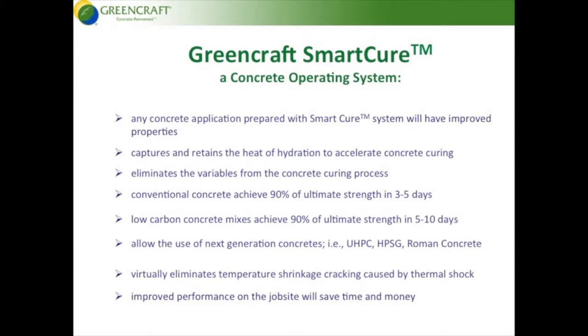You can accelerate concrete curing so you don't have to, in order to get 6,000 PSI in 5 days, when the structural engineer only needs 6,000 PSI, perhaps you don't have to use a 14,000 PSI mix just to get there in 5 days. You can dial down the powder, you can dial down the heat. In a system where you retain the heat of hydration, conventional concrete, as we can see, you can achieve the ultimate strength in about 3 to 5 days. Now, low carbon concrete mixes, 90% of ultimate strength in about 5 to 10 days. This operating system is going to allow the use of the next generation type concrete out in the field, not just in a controlled environment.